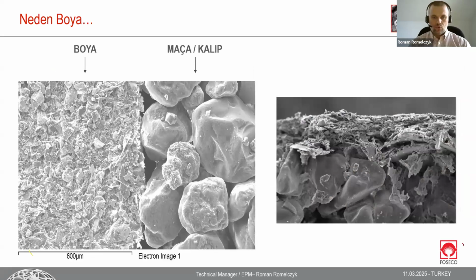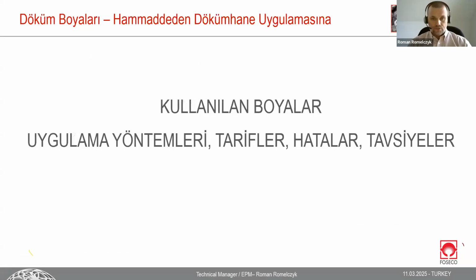The coating itself, at quite a big magnification, looks like this on the pictures. On the left side we can see the layer of the coating; the right side is, of course, the mold. On the right side of the slide we can see some other coating, more flaky. We can also observe some penetration, where the coating is sucked into the mold by capillary effect to impregnate the layer. That is how it looks. Yeah, application methods.